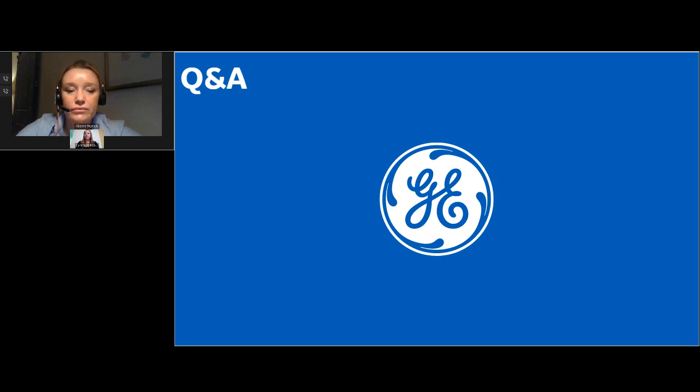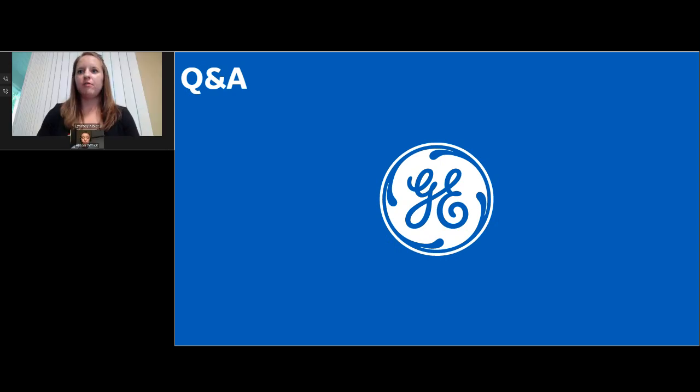Yeah, I think that's a great question. So as I showed before, there are definitely debits when you look at an as-printed surface in terms of fatigue capability. However, there are definitely several applications that are able to accept those debits and those as-printed knockdowns, even in a fatigue-loaded situation. So it definitely depends on your part requirements and the loading conditions that it will go through.